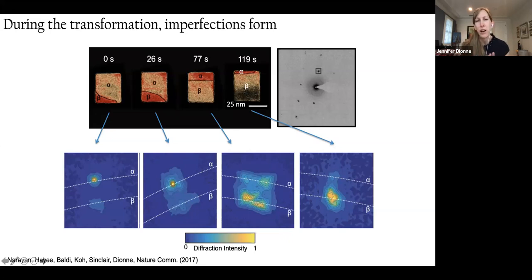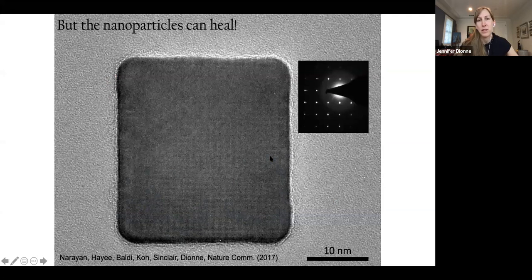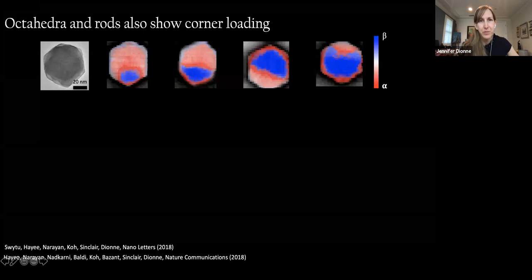So it becomes less broad. In some cases, it actually becomes smaller than the original particle. So this shows that the nanoparticles, at least below a certain size, have this ability to self-heal. So even though there's strain involved in this transformation, the particles can go back to being an extremely good single crystal at the end of the transformation.